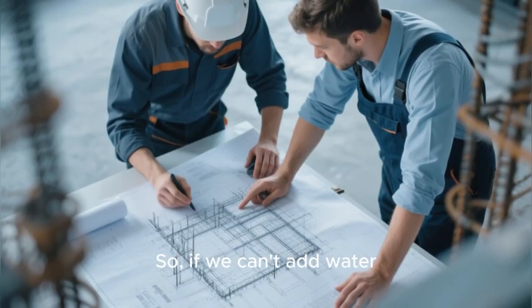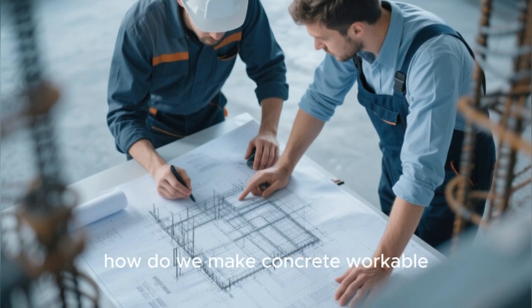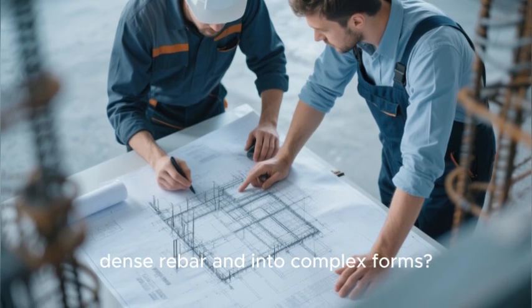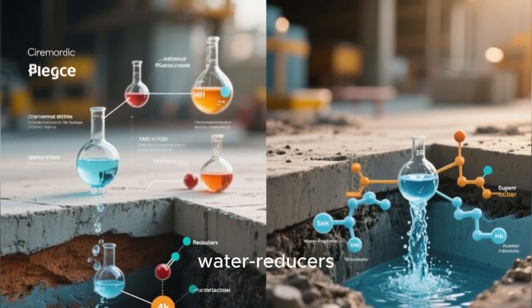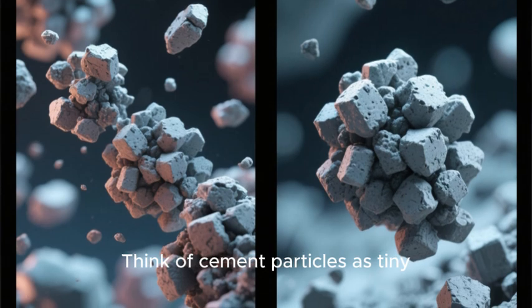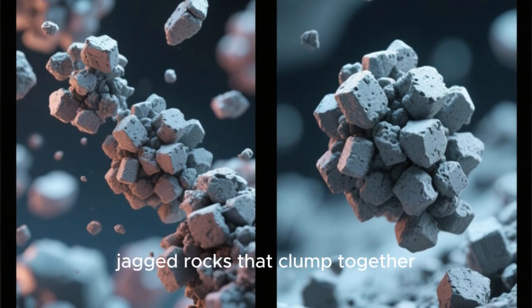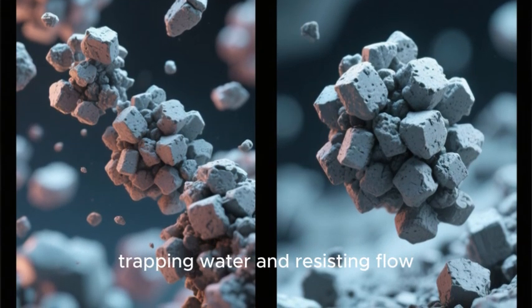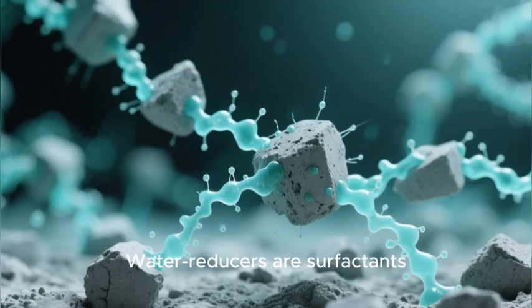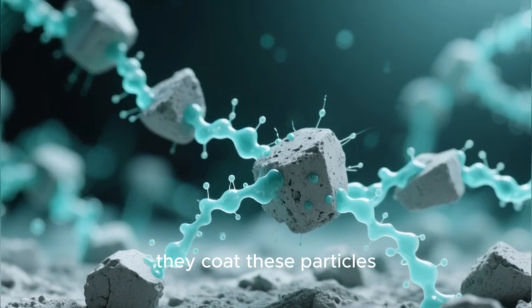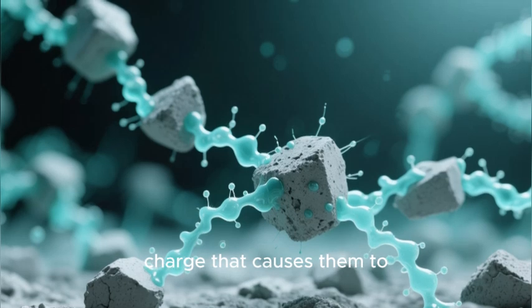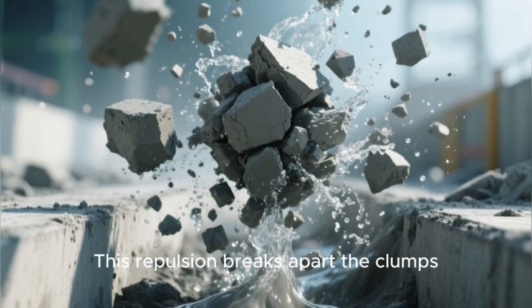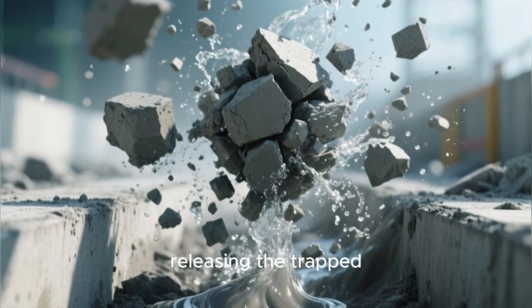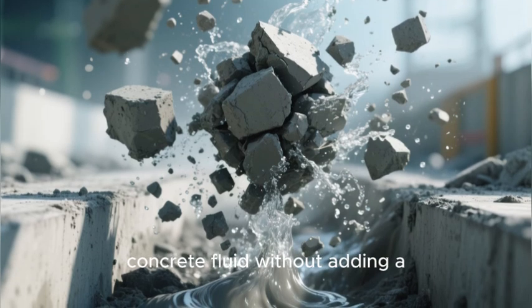So, if we can't add water, how do we make concrete workable enough to place around dense rebar and into complex forms? The answer is chemical admixtures. Specifically water reducers and superplasticizers, also called high-range water reducers. Think of cement particles as tiny, jagged rocks that clump together, trapping water and resisting flow. Water reducers are surfactants. They coat these particles, giving them a negative electrical charge that causes them to repel each other. This repulsion breaks apart the clumps, releasing the trapped water